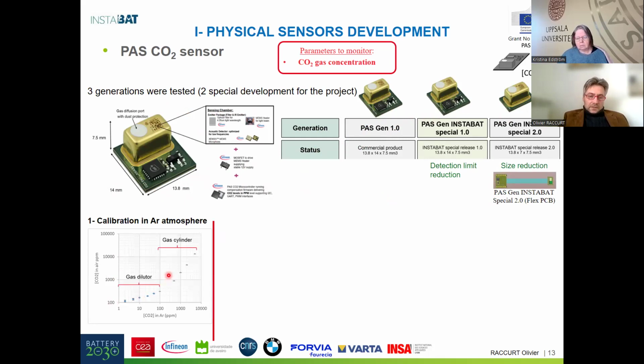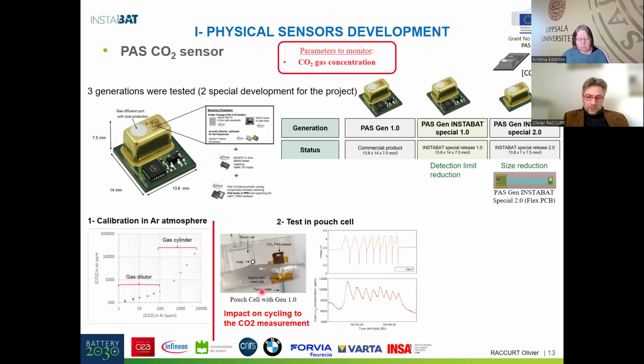We tested the sensor in an argon atmosphere because this sensor was initially developed by Infineon for measuring CO2 in air, not in an argon atmosphere or in an electrolyte atmosphere. And it's working well, but we need to change the calibration coefficient to measure the CO2 concentration.